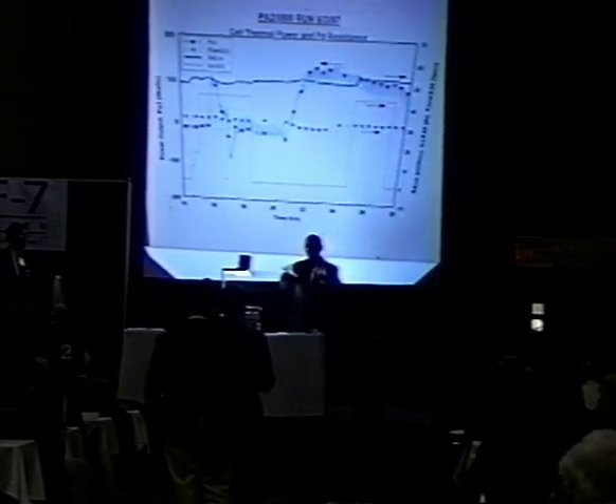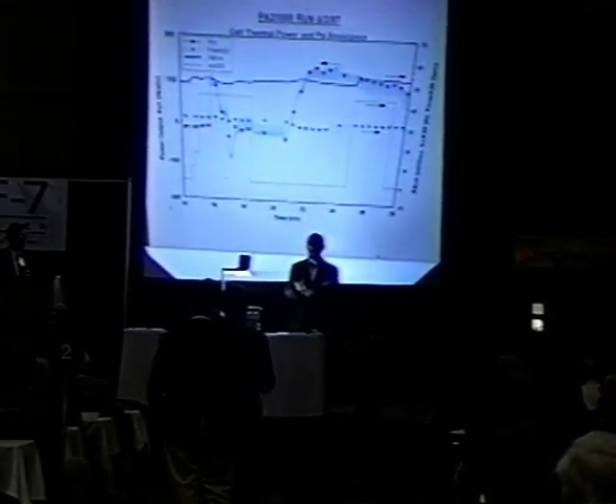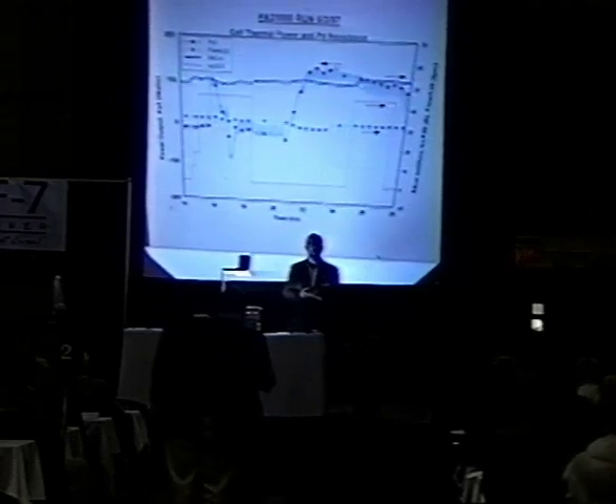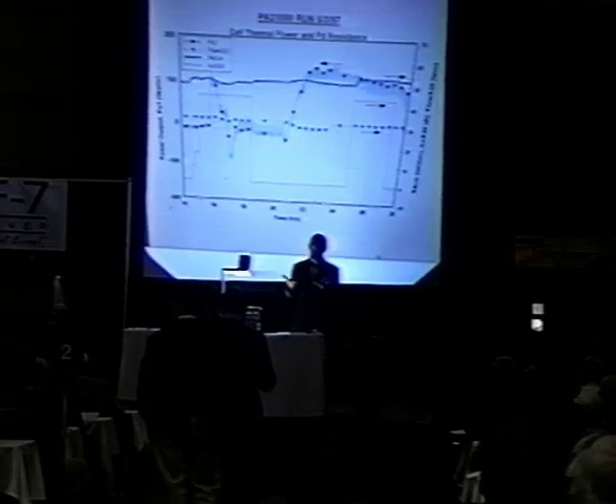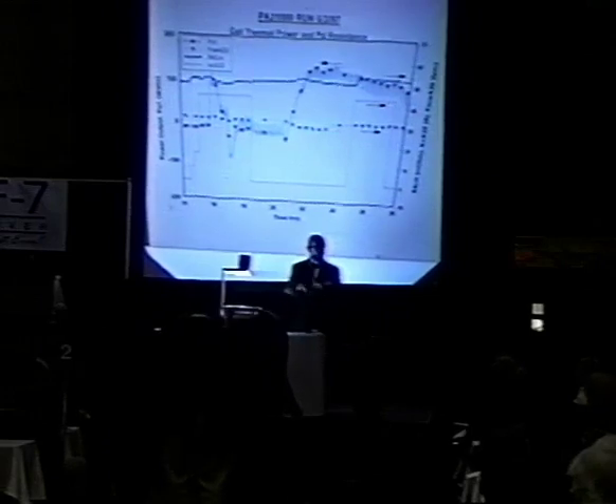But see, it's related. Remember I told you about the idea that this lithium carbonate is forming and appears to be reabsorbed somehow. I think that's a key feature, because in many runs I've done, I've actually taken solutions and run them with just electrolysis, those that produce no heat, and formed a lot of carbonate and took out 90% of the lithium. I took it over to the chem lab, they analyzed it, and only 10% of the lithium was left. Those produce no heat. But for some reason, and I think this may be a key factor, the carbonate that's forming is being redissolved. And again, the chemists I've talked with say the lithium carbonate does not dissolve in this solution. When it forms, it sinks to the bottom and sits there. In the runs that produce no heat, that's exactly what it did. It sinks like a rock. But for some reason, we got this dissolving.